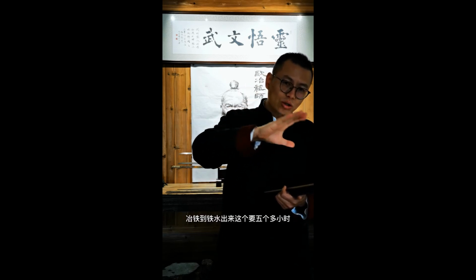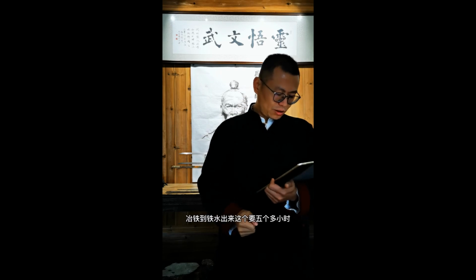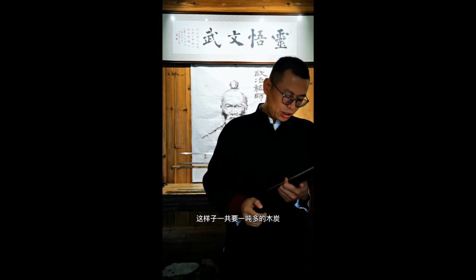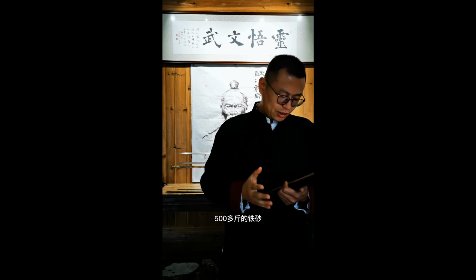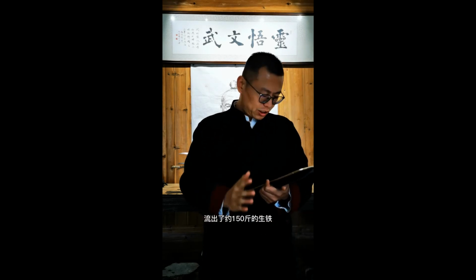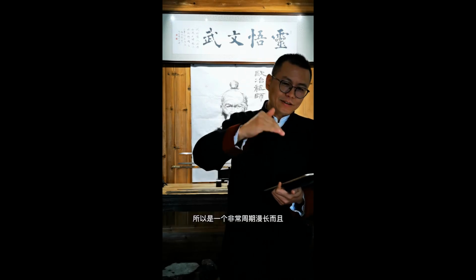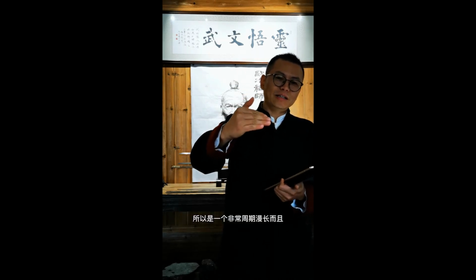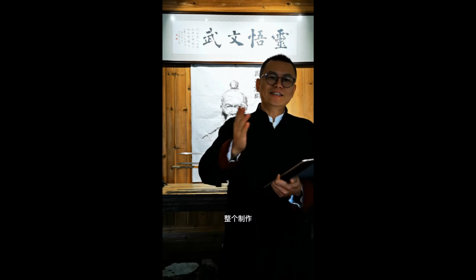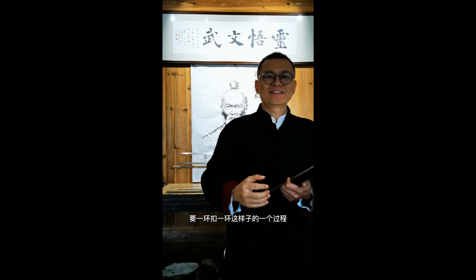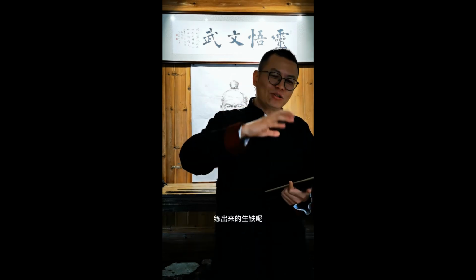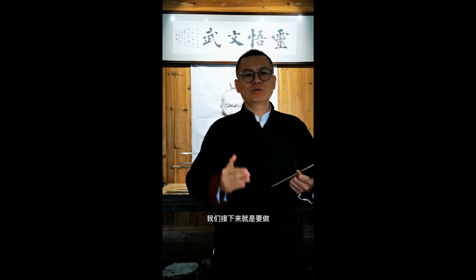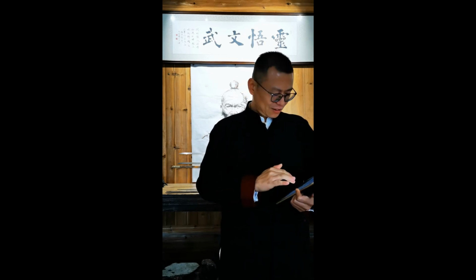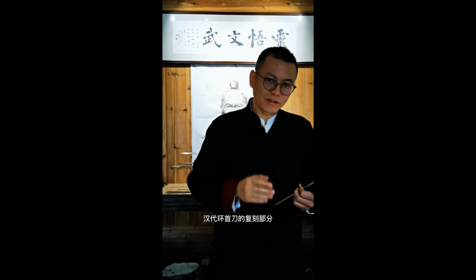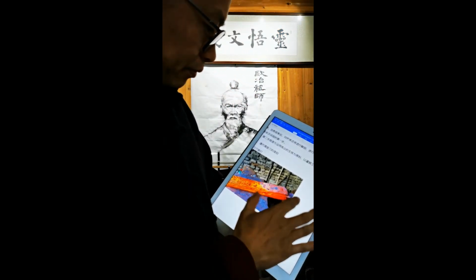From the first adding of ingredients to the last minute when the melted iron flows out, the whole process is about 5 hours, with 1 ton of charcoal and 500 jin of iron sand, generating 150 kilograms of pig iron. This is a huge project. So one step by another, followed by another. The pig iron we got was used as the raw material for the reproduction of a hand sword. Now let me show you how this sword was made.